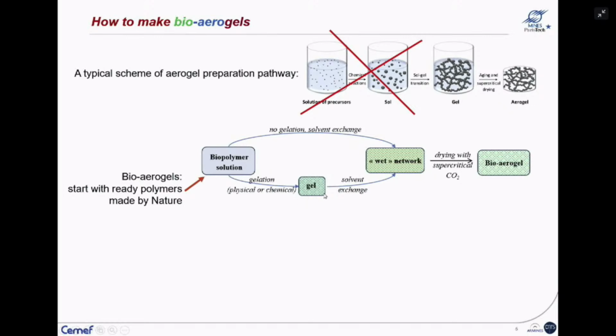You can gel your solution or not. And then as far as the solvent of polysaccharides, let's say, or many bio-based polymers, is aqueous media, and water is not miscible with CO2, it is necessary to do the solvent exchange, which means you have to replace water by a solvent which will be miscible both with water and with CO2, and usually it is acetone or ethanol.